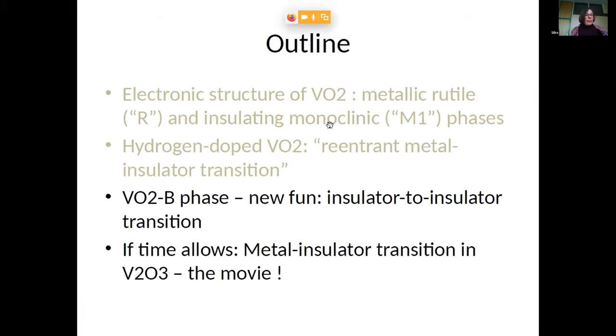You can summarize that by saying that, okay, if I compare the usual M1 phase now to the doped version where you get metallic, so you fill a bit the A1G and the EG pi states, and then you go to the D2 configuration in the fully hydrogenated case, you do have the bonding, antibonding splitting, the empty XZ orbital, and the YZ actually split into lower and upper Hubbard bands in the Mott sense. Okay, let me move on to the vanadium dioxide B phase, because I think I'm approaching the end, but I still have a few minutes.